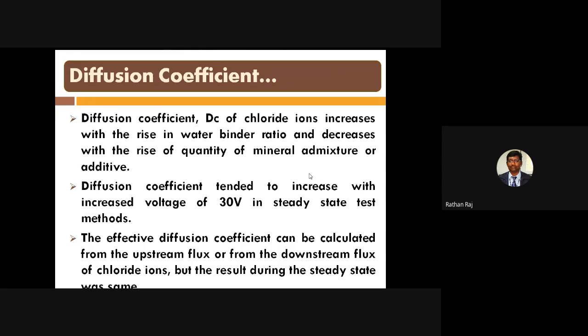The diffusion coefficient tended to increase with an increased voltage of 30 volts in a steady state method. When we maintain 30 volts in the steady state method, the diffusion coefficient value automatically increases. The effective diffusion coefficient can be calculated from the upstream flux or from the downstream flux of the chloride ion, but the result during the steady state was similar. We can see that elaborately here.